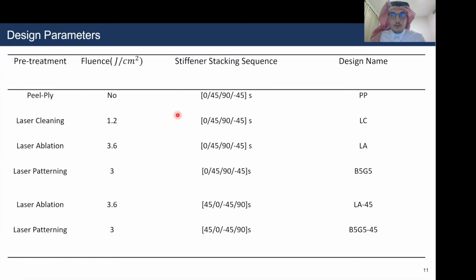The stacking sequences will involve quasi-isotropic stacking sequences, where four designs will have a 0-degree surface fiber at the interface, and 2 extra designs will have a 45-degree surface fiber at the interface. This will be applied to laser ablation and laser patterning. So in referring to the T-joints, I refer to PP as peel-ply, laser cleaning as LC, laser ablation as LA, and B5G5 as patterning. The ones which had a 45-degree surface ply are LA45 and B5G5-45.